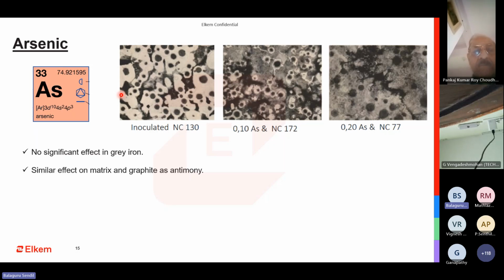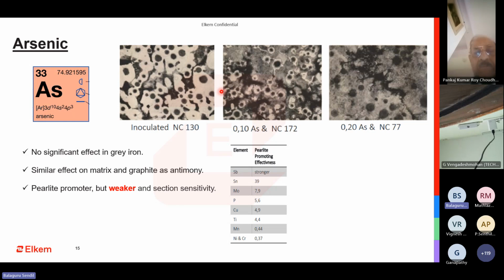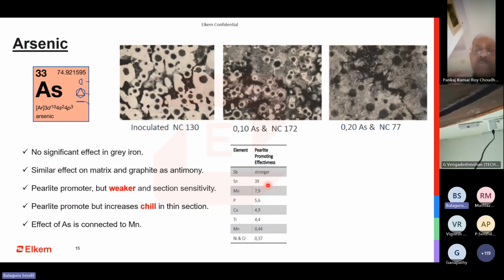It has a very similar effect as antimony, a very strong pearlitic promoter. It promotes pearlite, but it is not as good as antimony. It is much weaker, and it is very section sensitive. If you have thick sections, it will not do the work, whereas antimony will do the work, arsenic will not. So that is where this comes in. It is not at the top of the matrix. It's not even considered here. It promotes pearlite, but it is also a very strong chill promoter in thin sections.